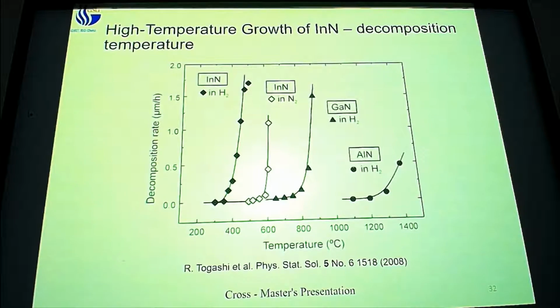This is a study done at atmospheric pressure, so it is a little bit different, but from most of the reading I've done, getting it to work above 650 degrees Celsius doesn't happen. The decay rate is much faster than the growth rate. Growth rate is a big problem as well because commercially, indium nitride is not a viable system yet. We cannot grow it fast enough to make it commercially viable so that we can make devices out of it at a large scale.